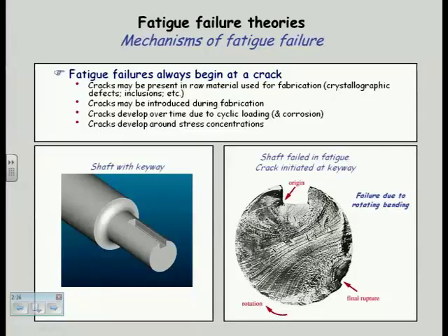This crack apparently grew and grew until all that was left to hold onto this thing was this little piece right here, and it couldn't hold it anymore, and it ruptured right here. So typically when you look at a surface that has fatigue failed, and I'm going to send some of them around, this is probably the nicest example I have, you will see this characteristic. Sometimes the beach marks will be all smushed away because it's been rubbing on itself during this process, and you don't always see the beach marks.